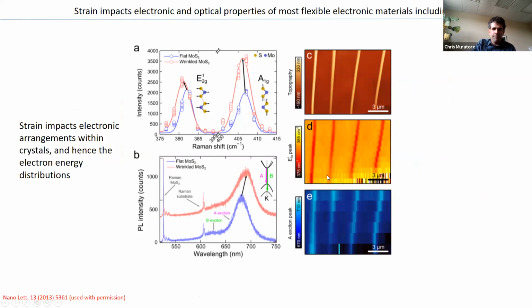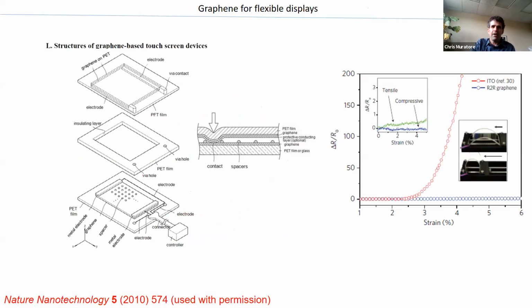So this is an example where the band gap in one of these 2D transition metal dichalcogenides shifts with strain. And that's important if you're counting on your device to perform a certain way. You need to know that some of the intrinsic properties of that material are not so intrinsic. When you strain them, they're going to be different. So you need to be aware of how the optical properties change with strain.